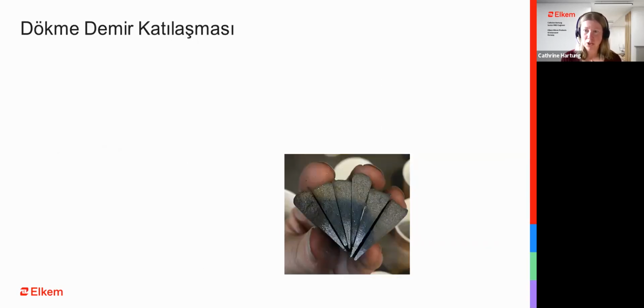With inoculation, what we want to ensure is that as much as possible of the solidification is taking place within the stable system, giving us carbon in the form of graphite, either in the shape of flake, compacts, or nodules. The effect of inoculation can easily be seen and measured on a chill wedge, as shown here. In this case, I am holding different chill wedges from an inoculation trial in gray iron, where we have used different inoculants on the same iron. And as you can see, there are different amounts of white in these chill wedges.